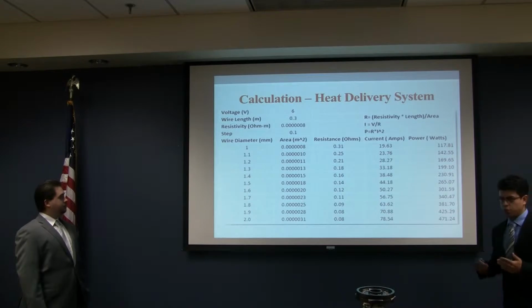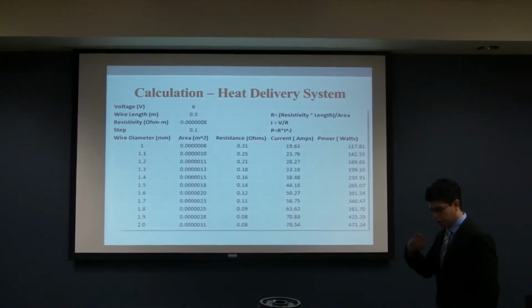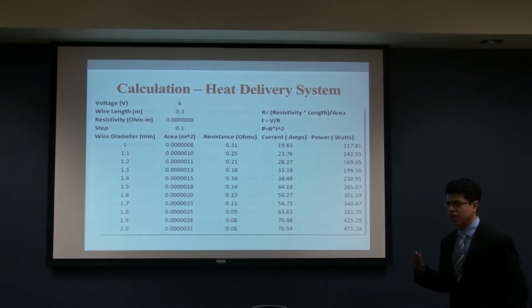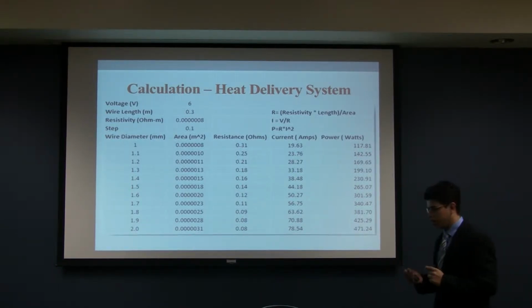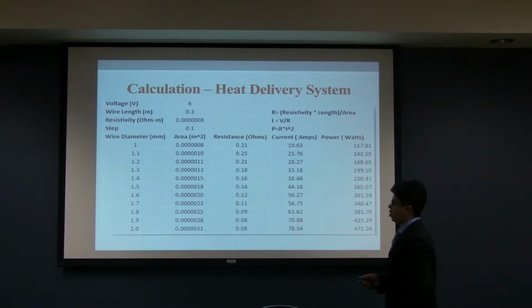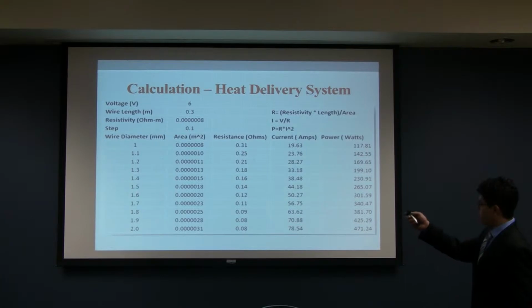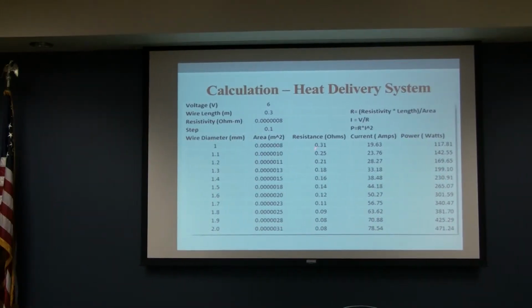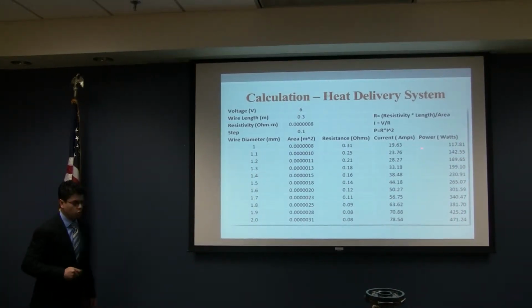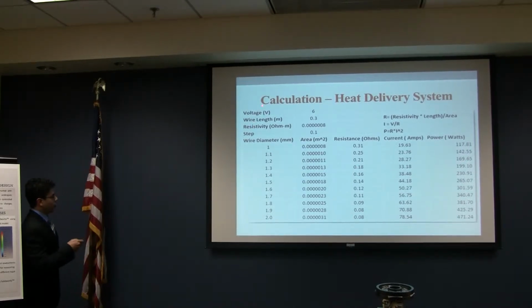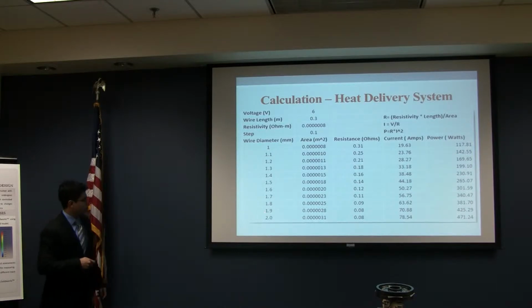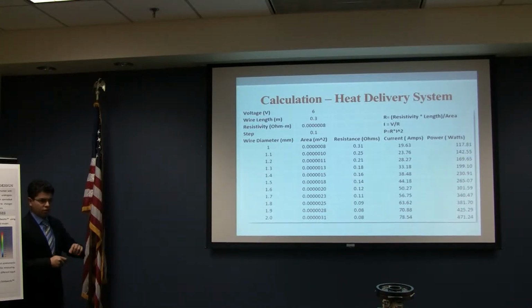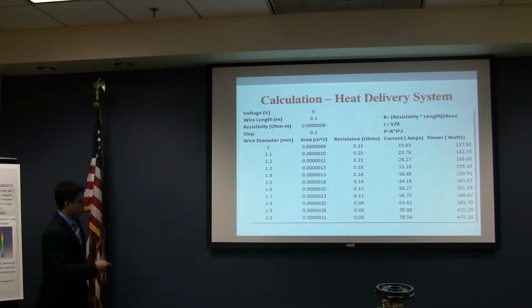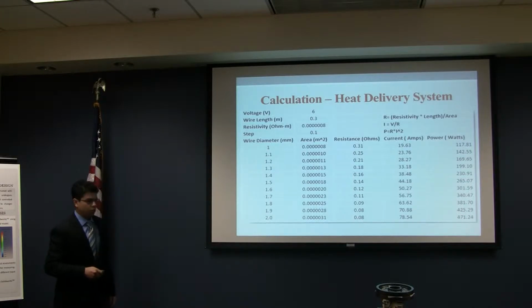The next step, after we have the springs done, we need to, I'm going to rephrase this. Before we make the springs, we need to know what is the size of the material. We need to use a wire form, so we need to coil the springs. In order to know how much energy or current we need to use, we need to calculate the resistance and how much amperage is going to pass through if we connect that to a power supply. So we iterated and we found that a very good diameter will be 1.9 millimeters. Finding the resistivity of the material, the length of the stretched spring, and the voltage, we could find all these parameters like the current and power. Using 1.9 millimeters, we estimated around 400 watts.